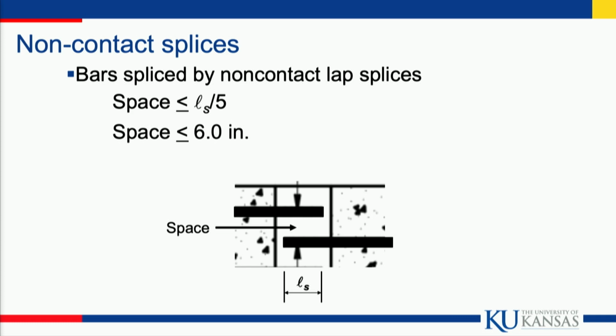Okay, so first let me talk about non-contact splices. In most cases, if you're dealing with a structural engineer, you deal with a contact splice. You wire the bars together. The wire doesn't do anything, but you wire the bars side by side, and you have enough length to give an adequate capacity. But you're allowed, both in AASHTO and ACI, to have non-contact splices. The rule there is the space between the splices has to be less than 1/5 the length of the splice, and the space also has to be less than 6 inches.